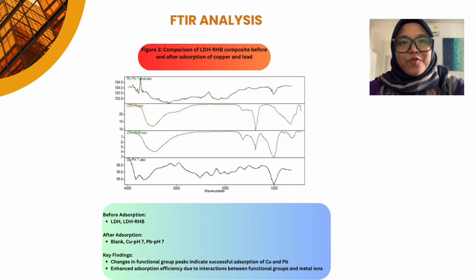This is the comparison of the FTIR spectra of the composite before and after absorption. This slide shows the spectra for zinc, magnesium, aluminium LDH and LDH with rice-husk biochar composite, as well as the sample after absorbing copper and lead ions at pH 7. The consistent hydroxyl stretching peaks and the shift in carbonyl and metal oxygen stretching peaks confirm the successful absorption of metal ions. This shift illustrates the formation of coordination bonds and highlights the enhanced absorption capacity of the composites.